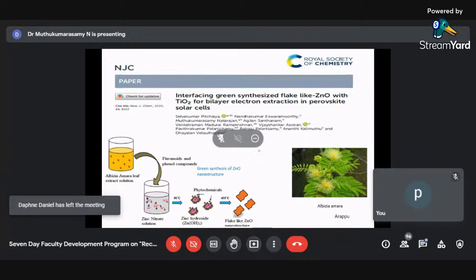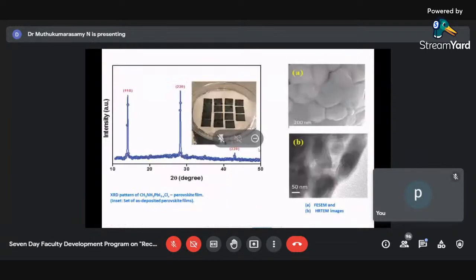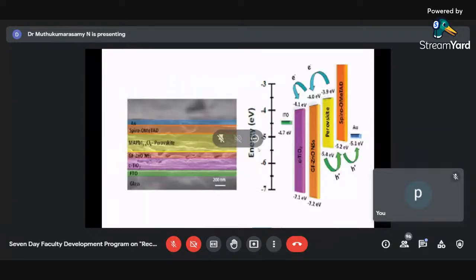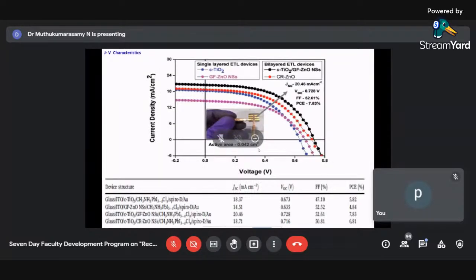And using the flake-like zinc oxide, we were able to fabricate solar cells. And these are the XRD patterns of the methylammonium, lead, iodide, and chloride mixed halide. And we fabricated a solar cell like this with glass, FTO, compact TiO2. Then zinc oxide was used instead of ordinary TiO2, which acts as an electron transport layer. We used zinc oxide, then mixed perovskite material, then spiro, then gold. And we got an efficiency of nearly 7.83, but we got a very good short circuit current.